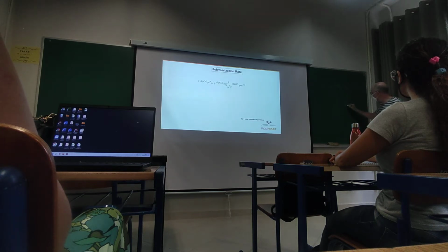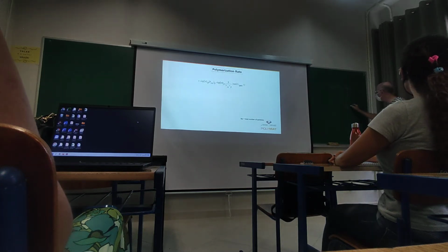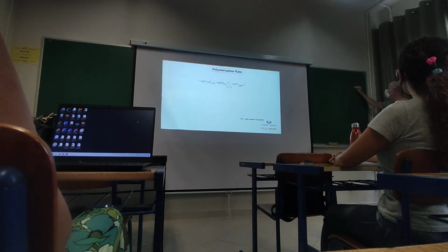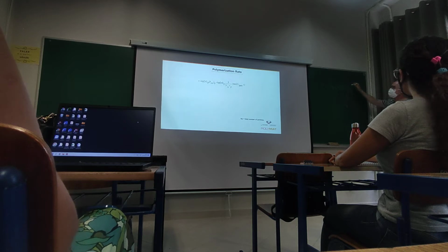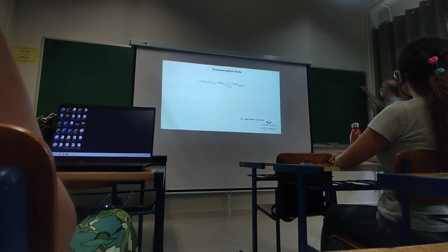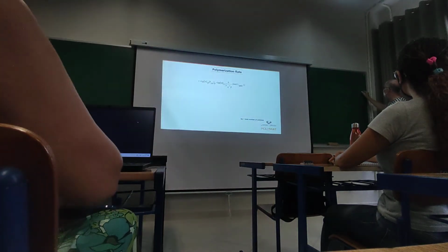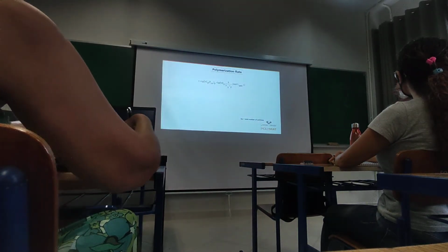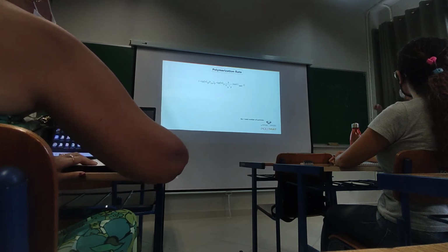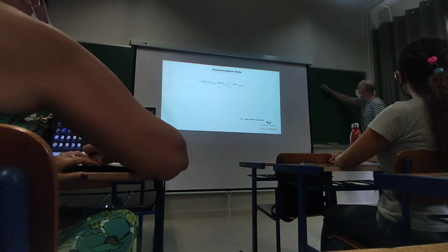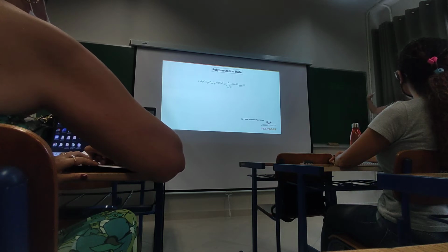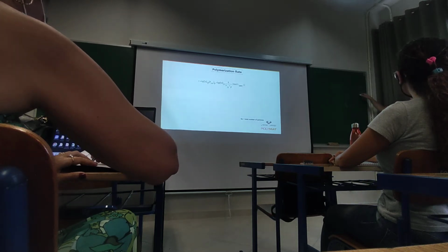divided by the Avogadro's number to convert the radicals into moles, and divided by the volume of the particle to have the right units. So the units of this expression are mole of monomer that react per liter of particle per unit of time, second. Okay? This is the rate of polymerization per liter of particle.